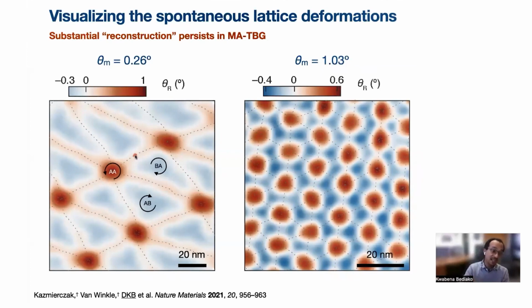And so sure enough, we can measure these and see that at AA sites, indeed, we have a further positive twisting of the Moiré superlattice, and then at these AB and BA sites, there's an untwisting. And so this was our first direct experimental measurement of the relaxation process that had been predicted from theory and that had been hinted at indirectly from some other microscopy measurements.